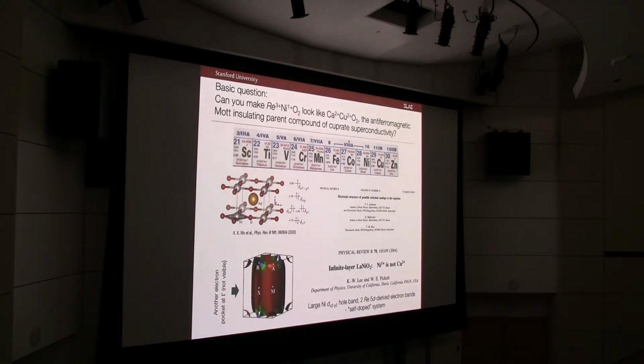So here's my periodic table, or part of it, and nickel is next to copper, so you may think that if I can make nickel 1+, it might fit and look like copper 2+. And indeed, that is the case. If I can make such a compound, I could have this planar configuration with nominally 9 d electrons, namely leaving an unpaired electron in the uppermost dx squared minus y squared orbital.